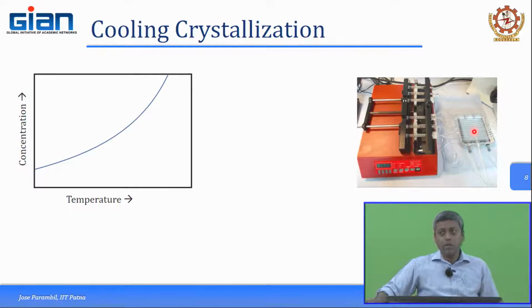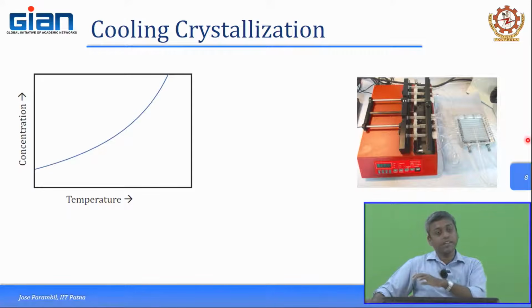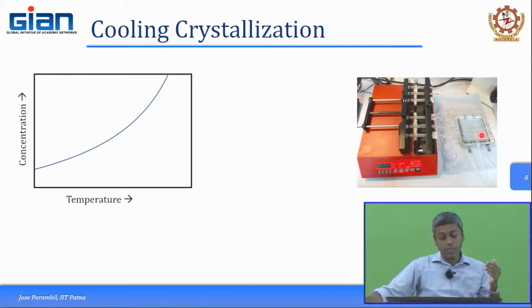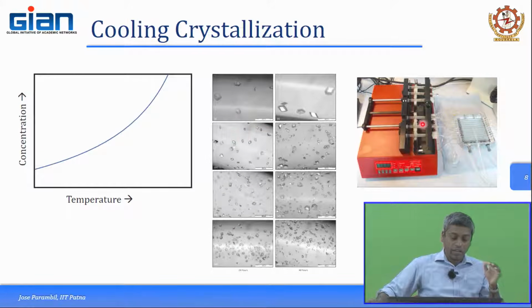These are few millimeter diameter tubings, temperature controlled with an external recirculator and so on. So, as it moves through the system, moves through the capillary tubes that you are providing, it cools down and it starts to crystallize. So, now the thing is, you can have systems, you can control the length of this system over here. You can make it longer or shorter, or you can take it out from here and then again cool it in a secondary chamber as well. So, by doing that, what happens is it starts to crystallize inside these capillary tubes, and you can get the crystals which start to form inside the tubes.